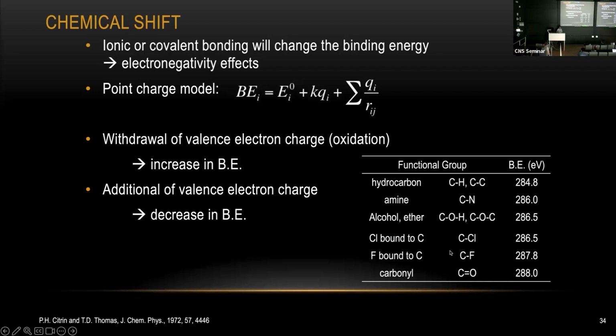Here is a very simple table showing a couple of binding energies for carbon functionalization. For XPS, we don't have enough resolution to differentiate between a C-C bond and a C-H bond, so they are all lumped into one single peak. That's why it's sitting around 284.8 EV. But if you functionalize your carbon material surface with some nitrogen and create some amine functional group, you can shift to around 286. And again, if you oxidize your carbon and create some kind of carbon double O bonding, now you can shift to 288 EV. All this energy shift is pretty much fixed. That's how you can compare your data to some database and find out what kind of chemical information you have.